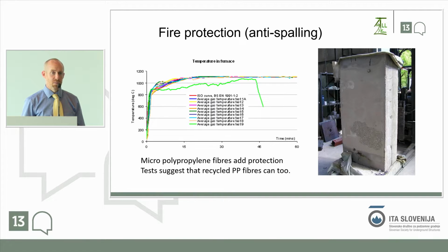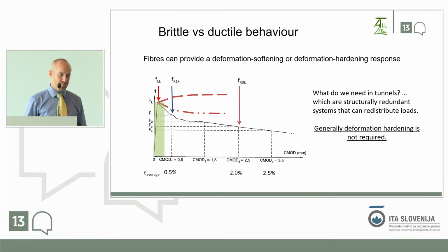Polypropylene fibres melt at around 100, 150 degrees, and one theory is that this allows the steam to escape. Hence you can see that this sample that's been put through one of these fire tests doesn't show that deterioration that you might expect from a bar-reinforced sample.